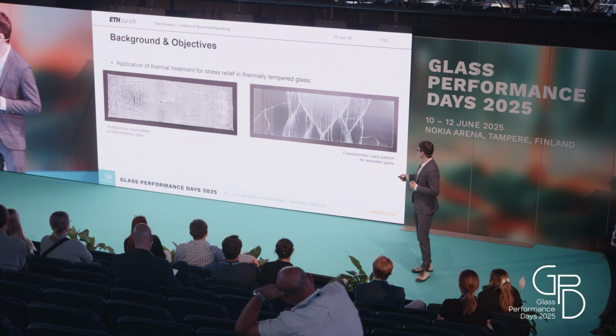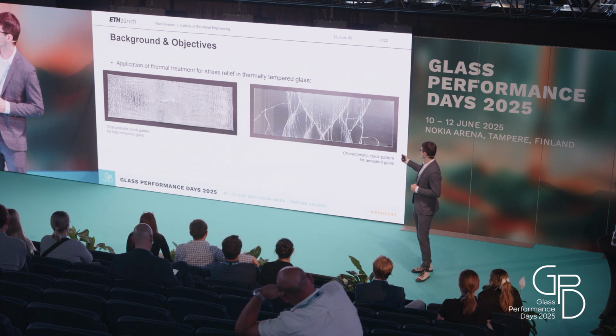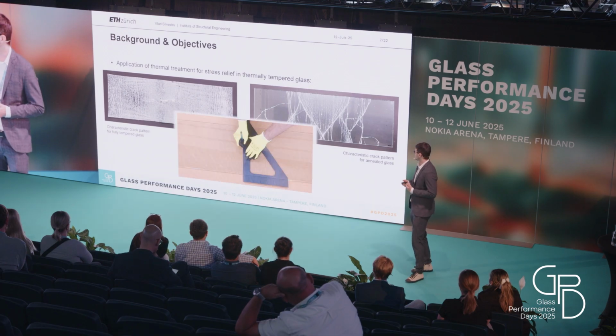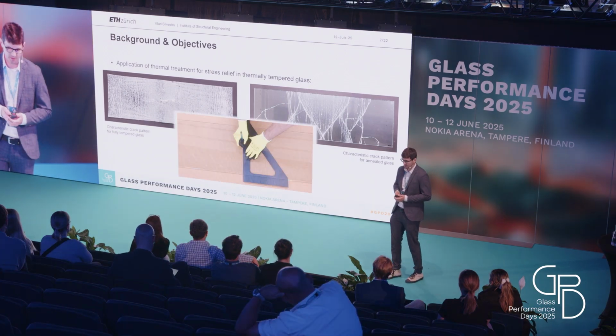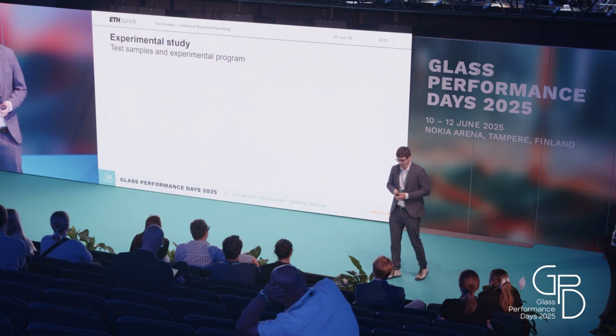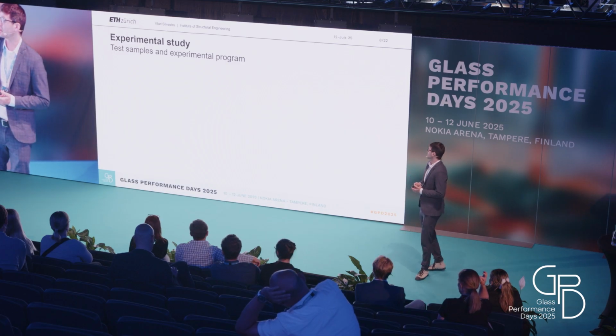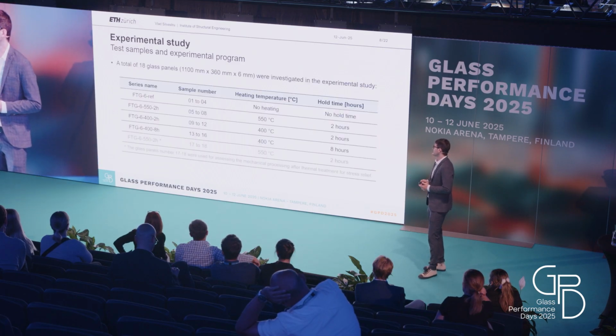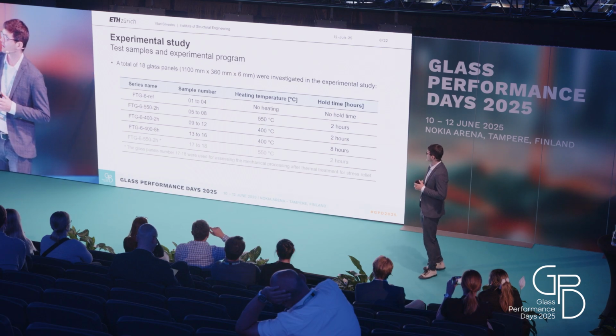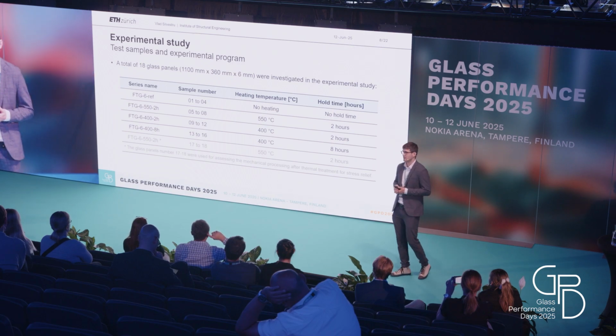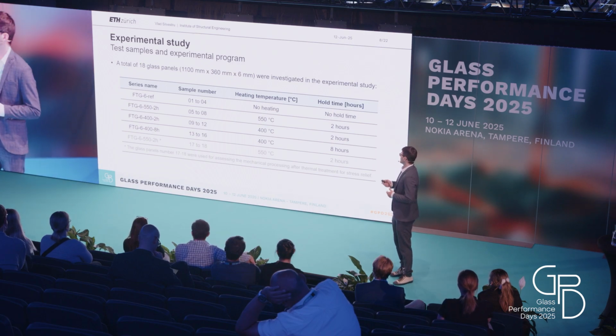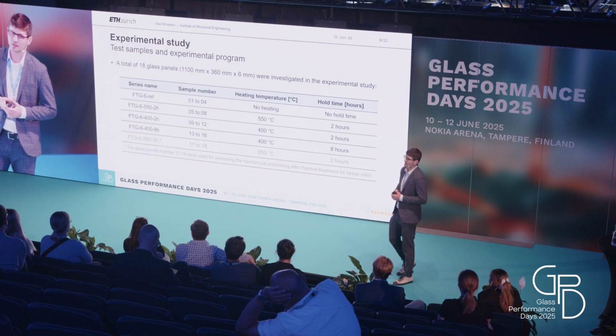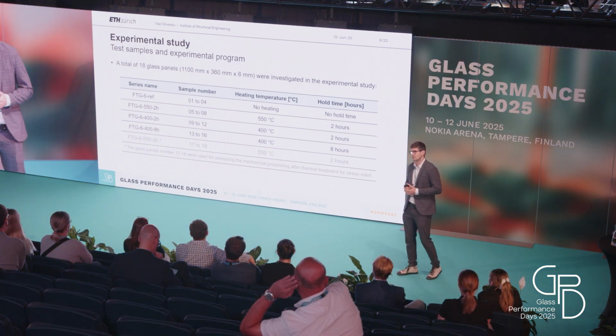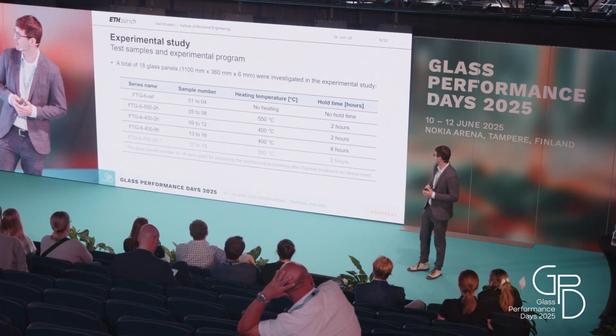So the question was, how can we get from this back to the initial annealed glass in order to basically be able to cut the glass? And for this, I conducted a study on different series. I used the glass panels 6 millimeter thick, fully tempered, with the sizes that are suggested in the EN 1288 part 3 for the 4-point bending tests.